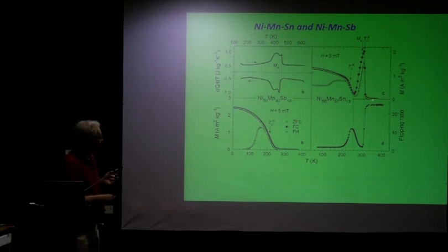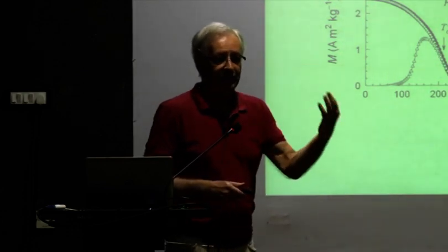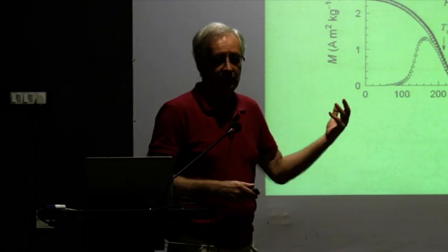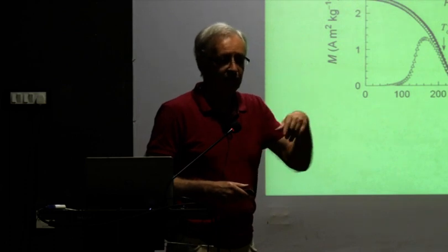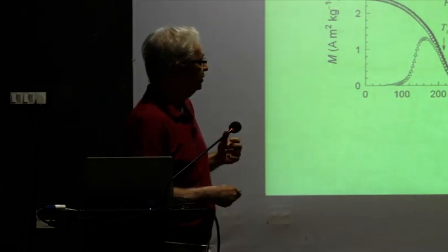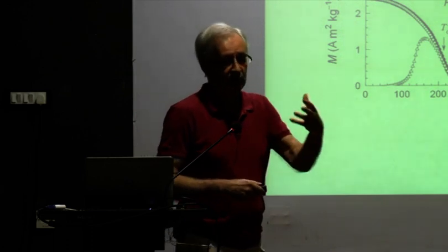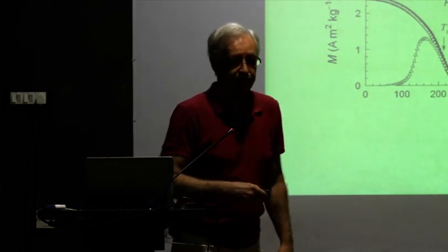You're up here in the paramagnetic state. The flipping ratio is something like this. It's 26. It's an arbitrary number because you're just counting neutrons, and the instrument itself has an intrinsic flipping ratio because the analyzers are not perfect, the polarizers are not perfect, and everything, and that is the maximum that you have. This value of 26 is the case when the sample is in the paramagnetic state, or if you have no sample over there at all, because all the neutrons go through without being depolarized.